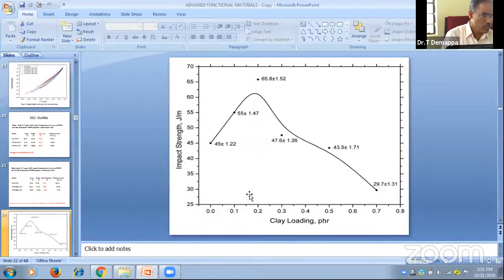This is improper curing, and also agglomerates and tactoids are formed, and they don't withstand the energy load or stress. That mechanical energy cannot be tolerated, and then there is collapse, crack formation. Micro cracks will develop. With further loading on the clay, the micro cracks will develop into macro cracks and collapse.